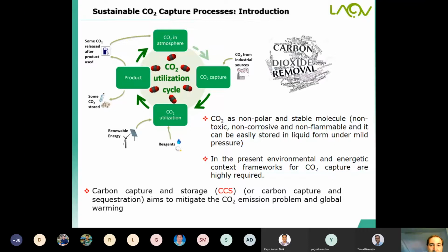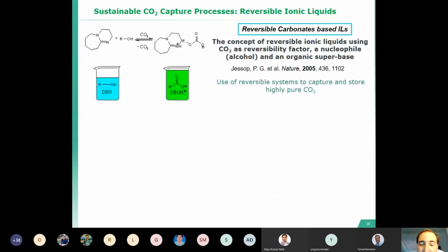In this context, some years ago, Jessop and co-workers published in Nature in 2005, this was 20 years ago, a very interesting concept of the reversible ionic liquids and salts. They show that it's possible to combine an organic superbase, in particular DBU, that you can see here in this reaction. It's possible to combine it with an alcohol that can act as a nucleophile, and in the presence of CO2, it's possible to obtain a reversible carbonate base ionic liquid, a reversible salt.